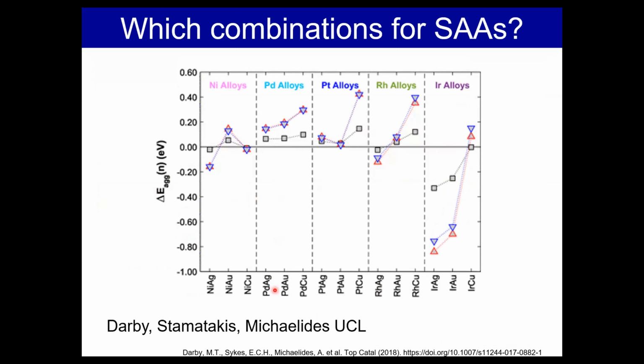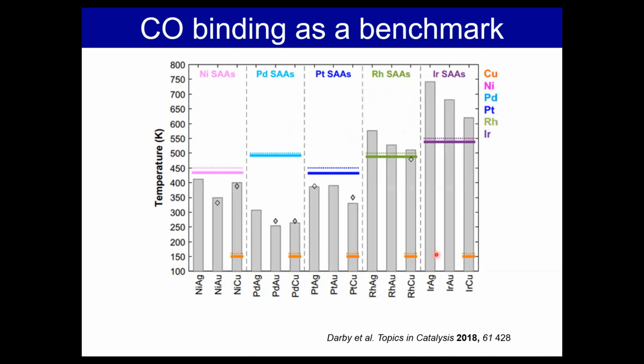And this is results from Michaelides' group showing that any alloys that lie above the line, this is the aggregation or the mixed enthalpy, any alloy combinations that lie above the line should be atomically dispersed, and any ones that lie beneath the line should segregate into, for example, iridium and silver areas. And one thing we use to benchmark the DFT calculations is the binding energy of CO. The gray bars here are the results of DFT parameterized KMC simulations for the desorption of CO. And then the diamonds here are the ones we've measured experimentally so far. So we get very good agreement for the binding of CO to these different single atom alloys as predicted with